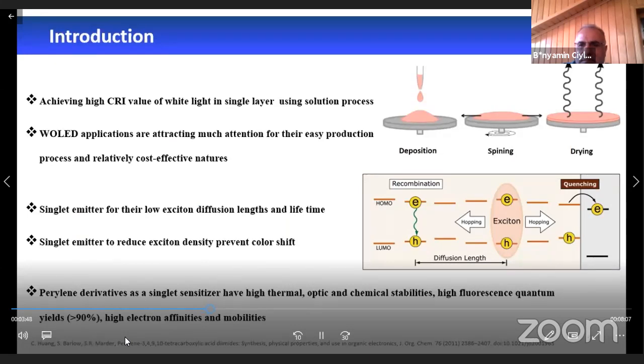Spin coating is one of the most used methods to fabricate an OLED. Coating thickness can be controlled by the concentration and rotation speed. In the previous slide, I said that the phosphorescent materials are more efficient. However, fluorescence materials have a significant advantage in white light production.